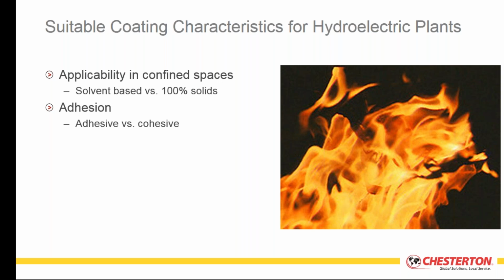We want to make sure that the coating system itself has very high adhesion properties, because the most common mode of failure of any coating on the surface is loss of adhesion. It tends to delaminate. Sometimes that loss of adhesion is due to improper surface preparation or the degree of surface preparation that was accomplished. But it's very important to ensure you have very high tensile adhesion forces of your coating system to get a positive bond to the base metal to provide long-term performance.